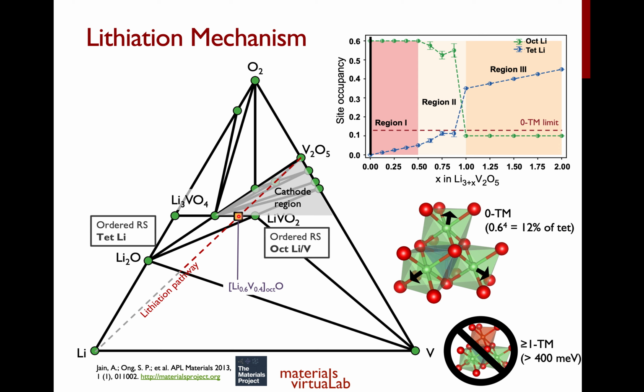Okay, we are essentially at this yellow dot over here. The rock salt formula, as I mentioned before, is Li3V2O5, right? Now, what we found was that when we first insert lithium into a tetrahedral site, the most favorable site for lithium insertion, unsurprisingly, is the zero transition metal tetrahedral site. Okay, so this has the lowest site energy for lithium insertion. This is the most favorable site, and this constitutes about 12% of all the tetrahedral sites in Li3V2O5.